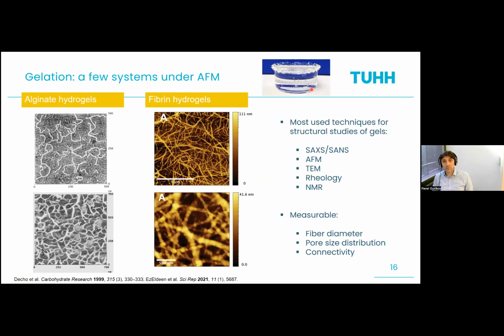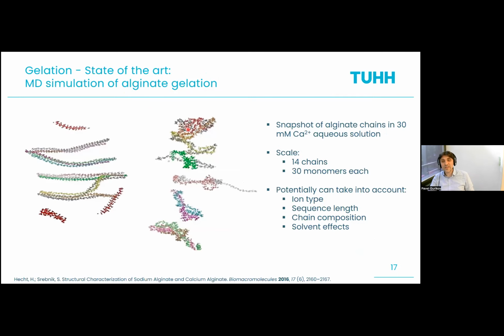And the only thing I want to tell you about modeling, the deeper you go, the more sophisticated it gets to model realistically things, for example, like gel formation. Why? Simply because they take place at different scales. So you see a typical hydrogel structure. The hydrogel contains these fibers, and the fibers are pretty small. And what your modeling can access is only a tiny part of this, maybe 50 nanometers, as in the case here from the literature. So you may see only formation of one or a few single fibers. So you can't really model the entire structure, but it does matter. We want to know what the pore size distribution is, what the thickness of the fibers is, all these kinds of things.